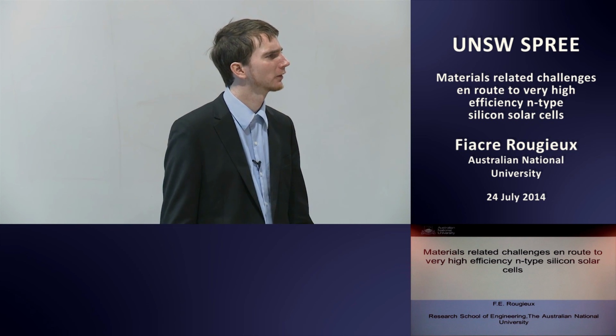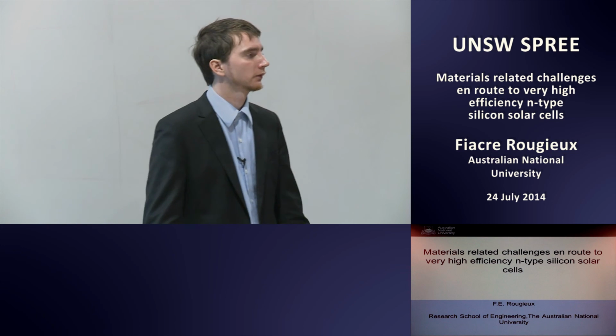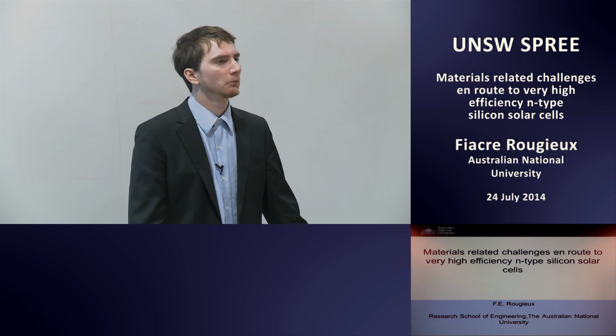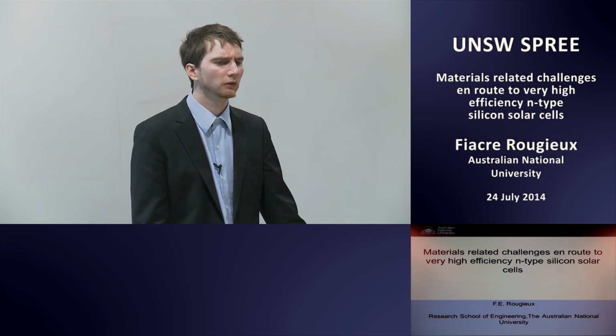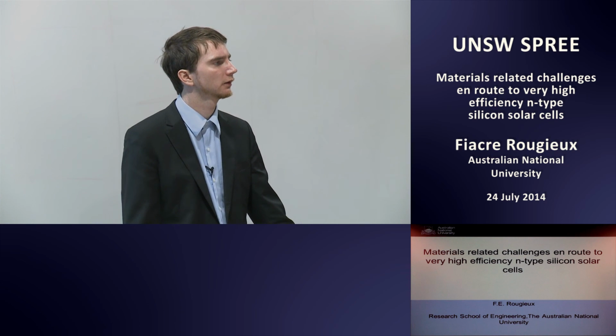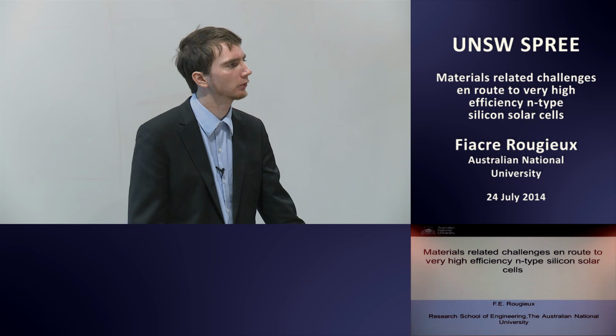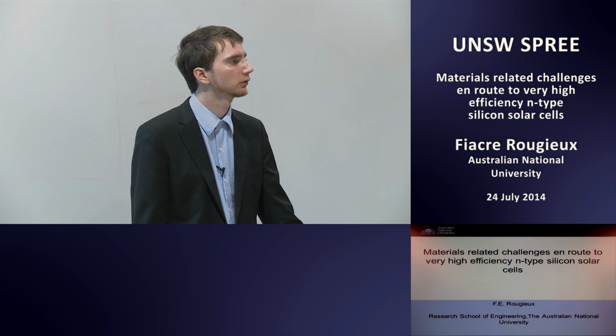The annealed lifetime is stable. So if you remeasure the sample and you just left it, yes, the annealed lifetime is stable. I do remember us trying to do some light-induced degradation, and we didn't see a change that I can remember. So the annealed lifetime is stable, but when we try to recreate the defect, we were unable to do so.